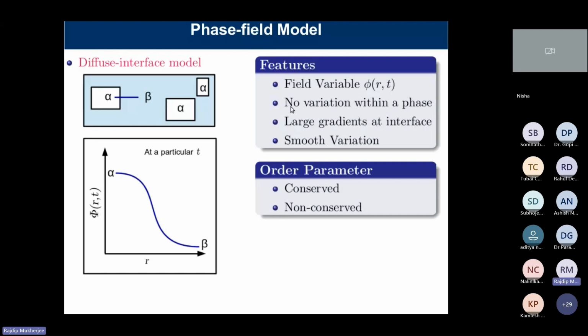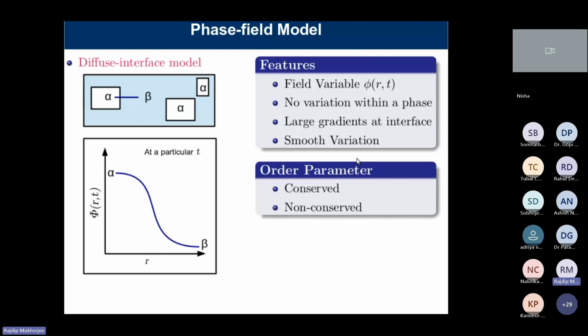This field variable is a continuous variable in space, and it changes in a diffuse pattern as you go from one phase to another phase through an interface. There is no variation within a phase, and a large gradient at the interface, but this variation is always smooth. Microstructure evolution works when the interface moves. If the interface moves, alpha will grow inside the beta phase. So we track the evolution of these field variables, and if we plot them, we get the microstructure evolution.